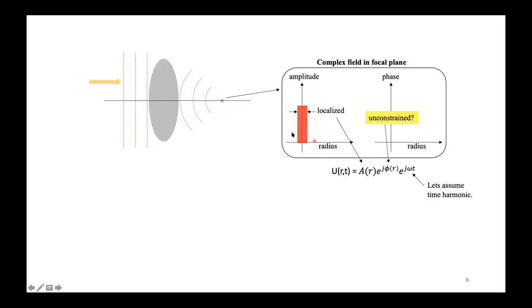And again, I'm plotting this in a radial coordinate system, assuming radial symmetry for the sake of simplicity. However, the phase itself is actually unconstrained, or so it seems. And the reason is quite simple, right? Because when you do imaging, you actually take the field and take the absolute value square of it to get the intensity, and that's what the vast majority of sensors will record. In other words, when you take the absolute value square of this field, the phase is essentially gone, right? You square it, it's gone. So on paper, you can say, okay, this is not terribly important as long as the amplitude is localized.